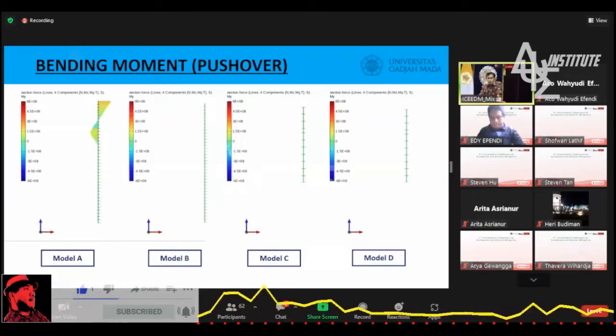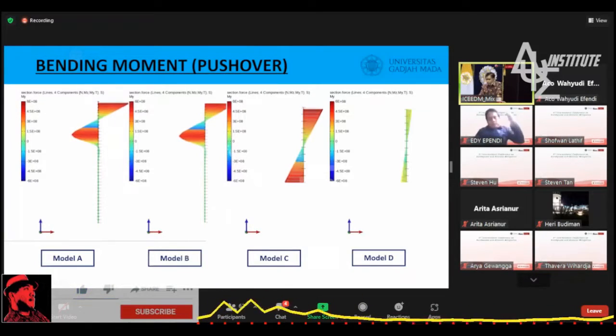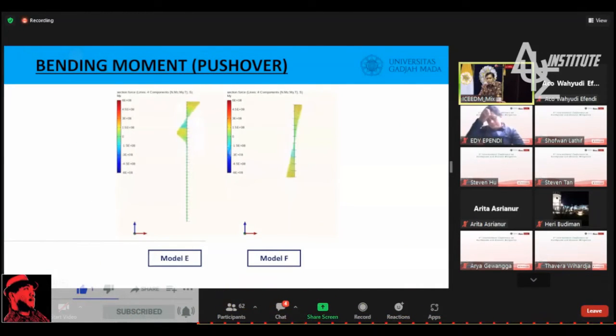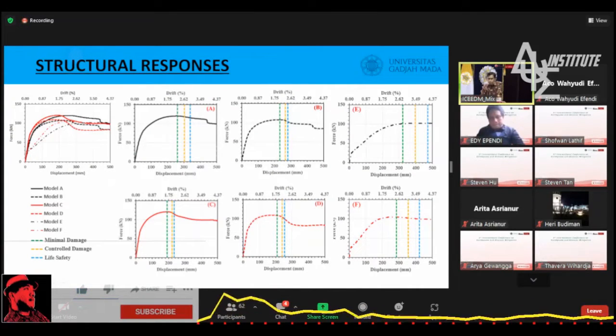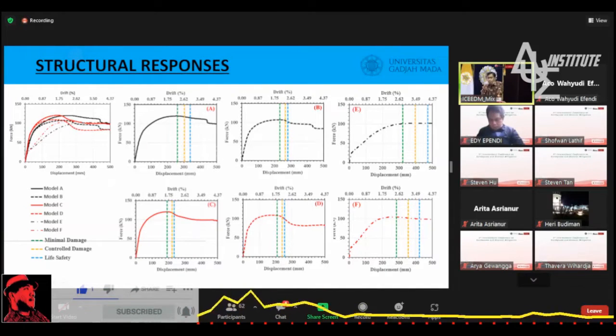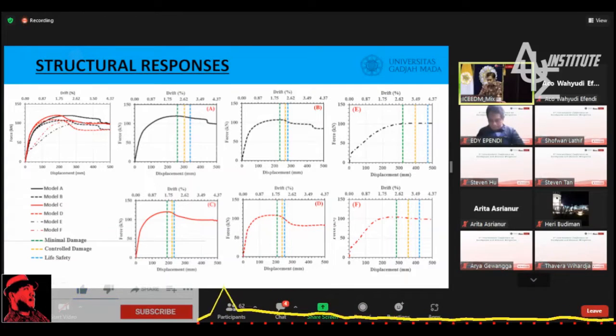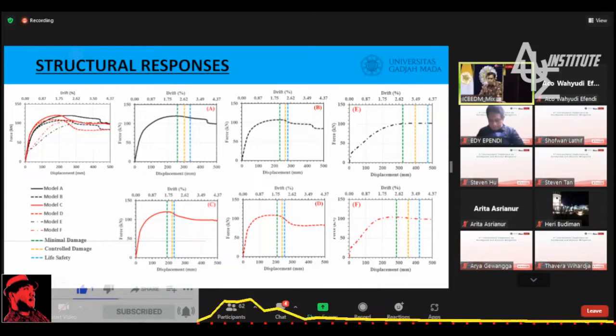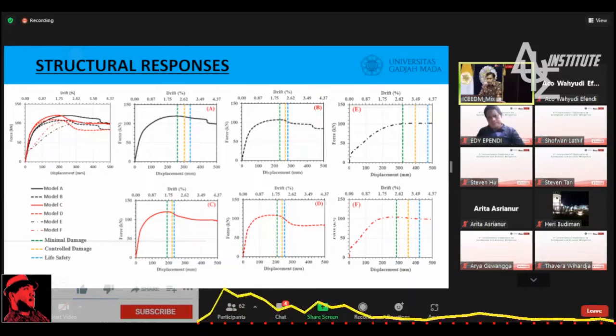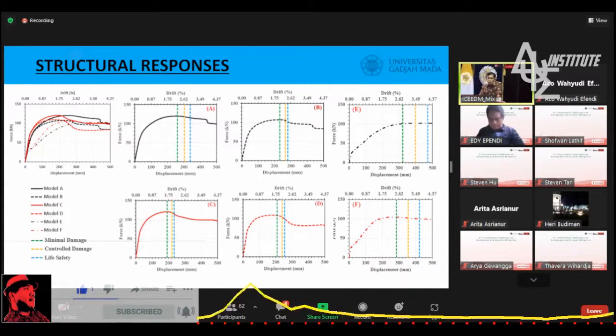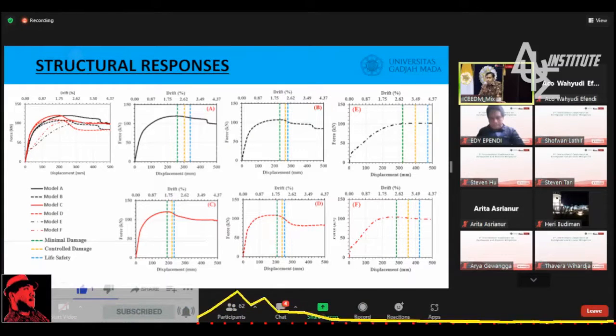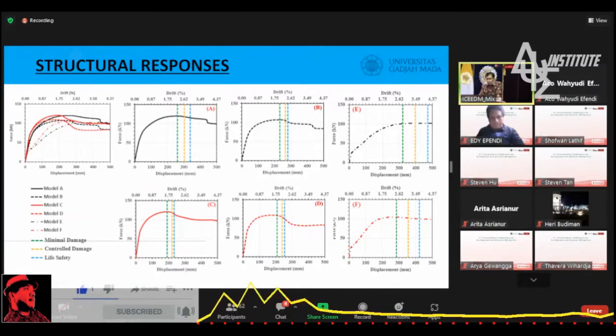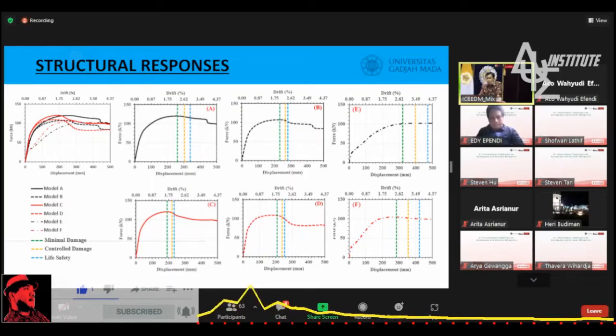And here we can monitor the comparison of the skeleton curve under pushover analysis. We can see that the spun pile has stronger stiffness, as the crack may be covered by the pre-stress effect, while in the RC pile the crack occurs and the stiffness decreases initially. However, looking at the post-yield stiffness characteristic, with the spun pile the drop of stiffness or strength degradation occurs earlier than with the RC pile. And when we compare model A and model B, the lateral strength with concrete infill is slightly larger than without infill, but not so significant.